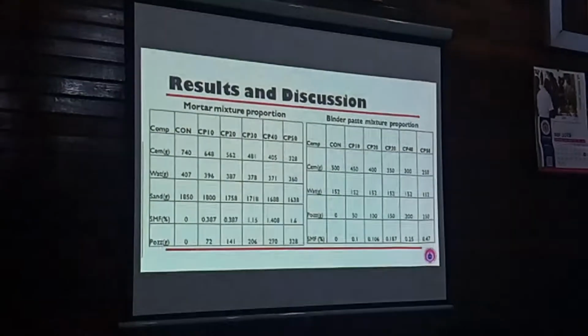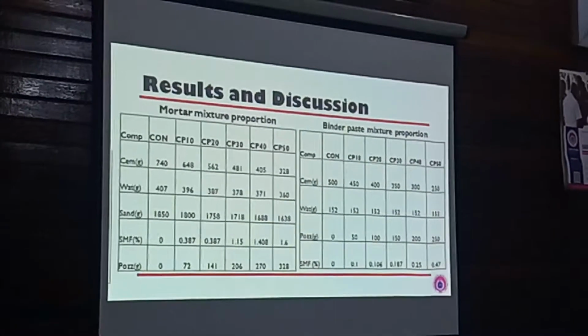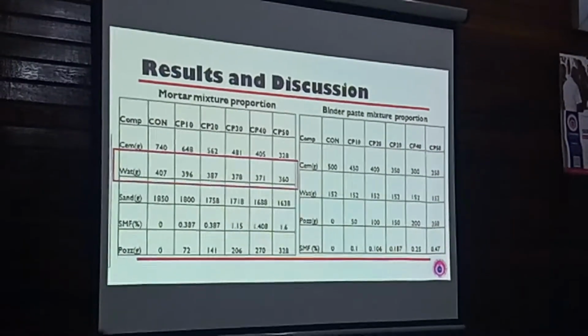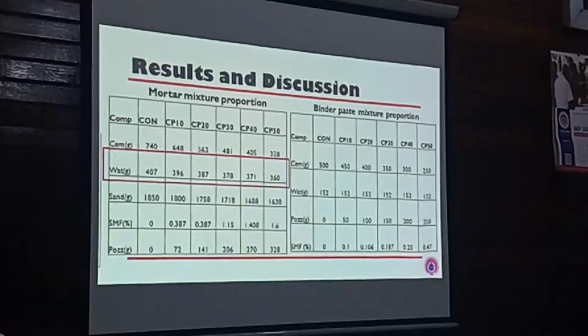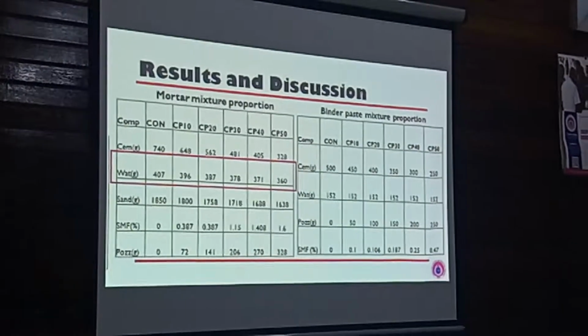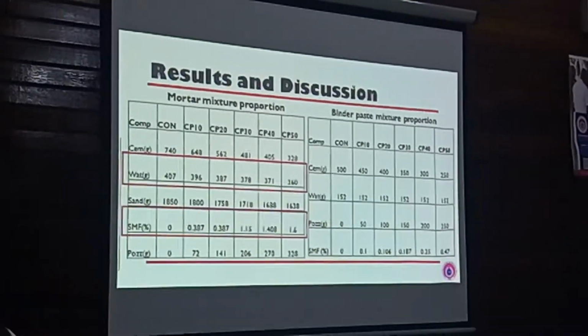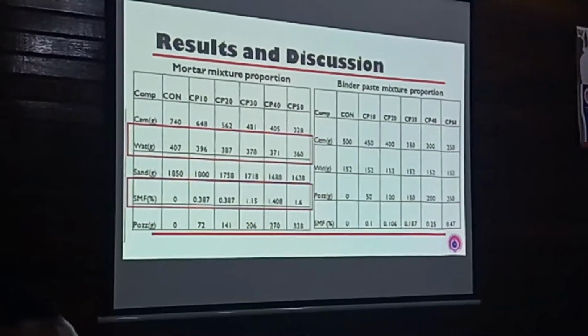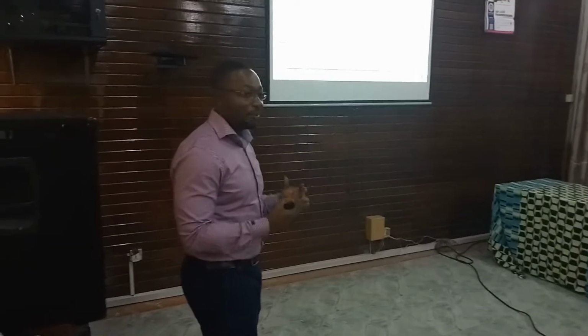Now the results. So these were the mix proportions. If I come to the mortar, the mix proportion in grams is shown here. But the point of interest here is that you can see the water was reducing as the percentage of pozzolans was increasing. In the same way, as I introduced the sulfonated naphthalene formaldehyde, it also increased. It means that the pozzolan that I have used is more or less very porous. So when the material is porous, it will attract more of the admixture. But don't forget that I'm trying to reduce water content to achieve a high strength. Don't also forget that when the water content is too high in a cement mix, the strength comes down. So that is the balance I'm trying to take.